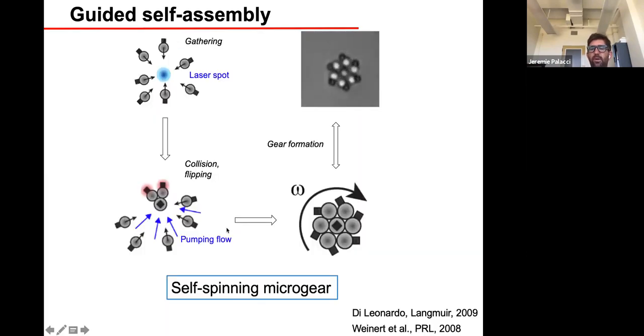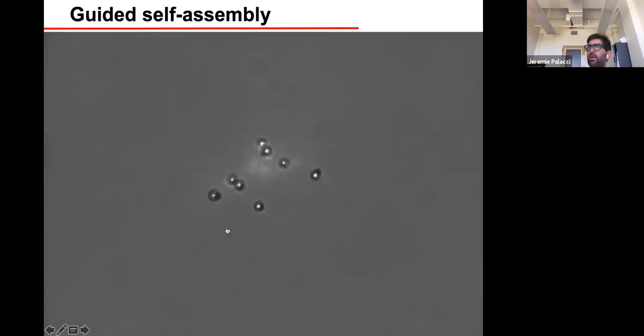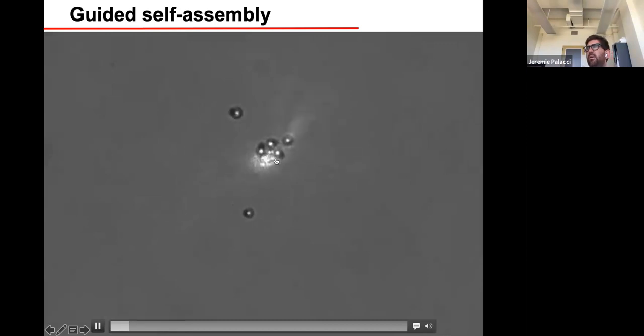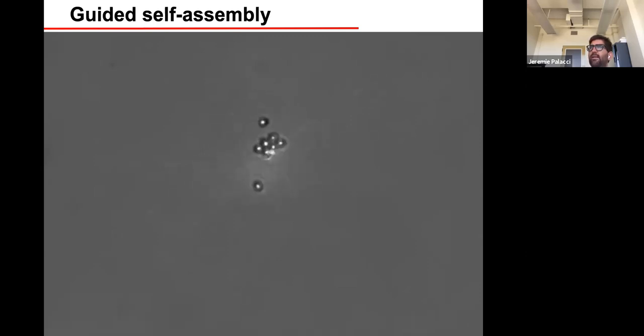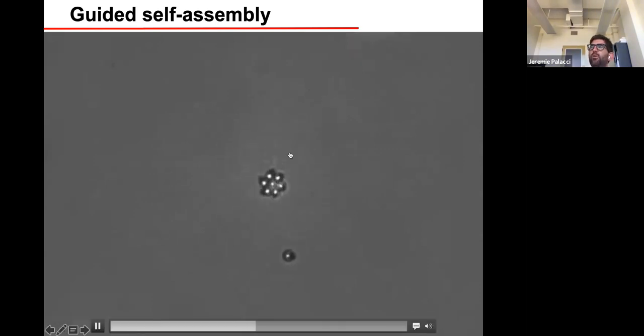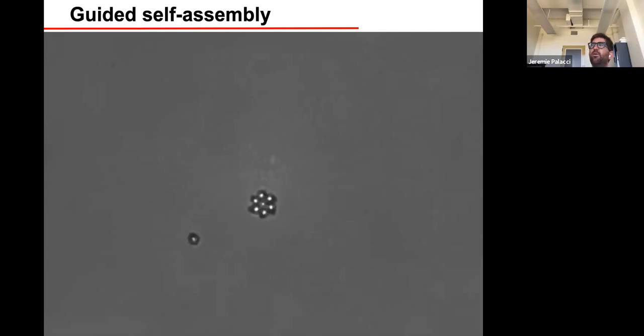I'm going to replay the movie once, because I think it's a really cool movie. You see that all the particles come near the spot and then they collide and form, and then they break down again because they didn't form the adequate structure. Eventually they form a microgear made of one particle in the center, which is flipped, and six at the periphery. Then the structure is stable and starts spinning. We have zero control at this point. I will discuss how we can have control, but at the assembly stage, we get clockwise and counterclockwise microgears completely randomly.